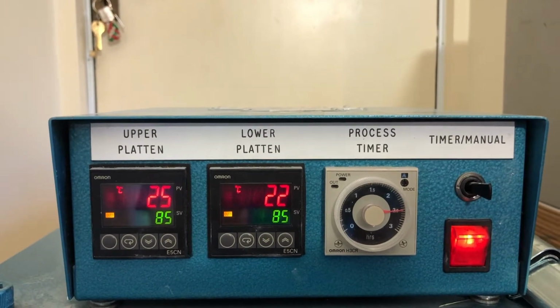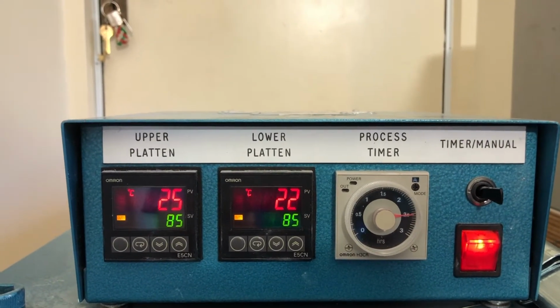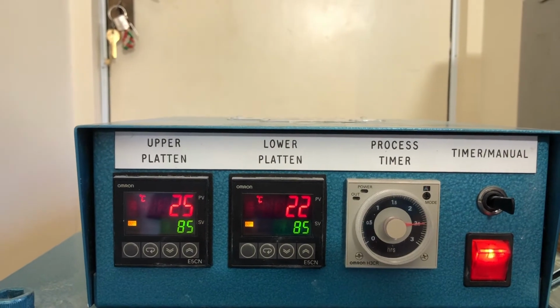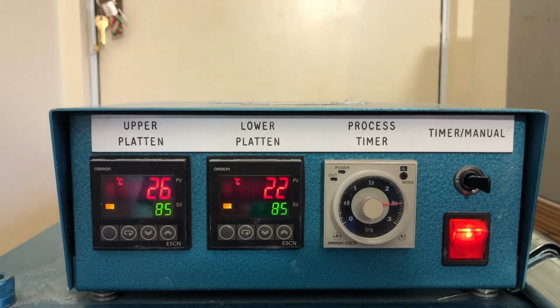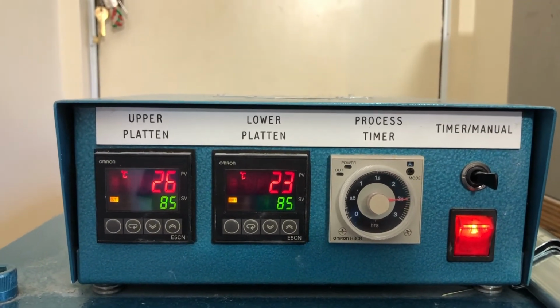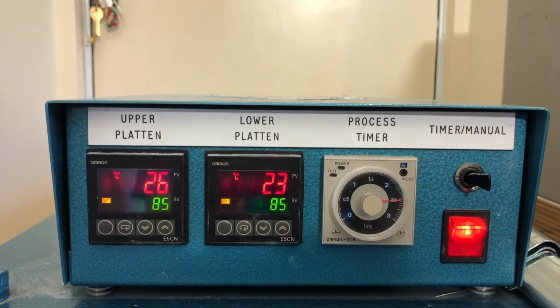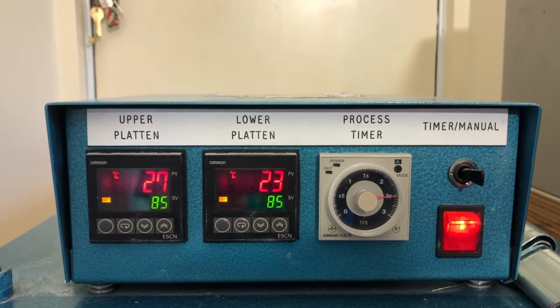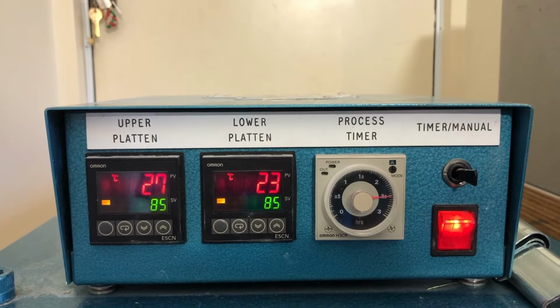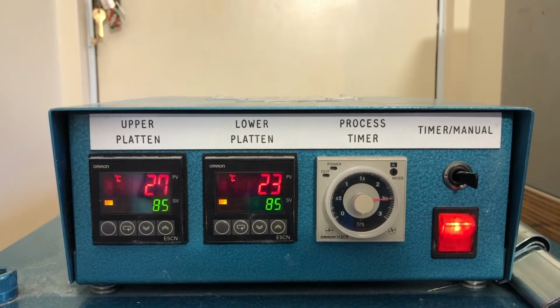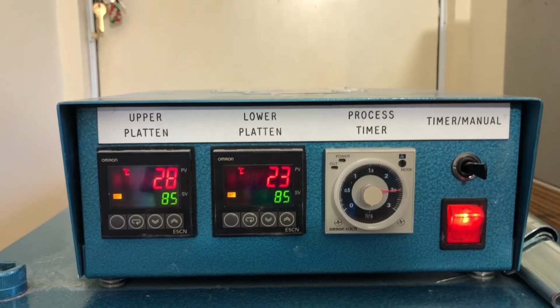So I tend to prefer low temperature silicon, and I'll get away with less than 1% shrinkage if I do it this way. So the figure is more the size that it was when it started. Right, okay, I'm going to go off and finish laying out the mould, and I'll be back when the temperature's reached 85 degrees.